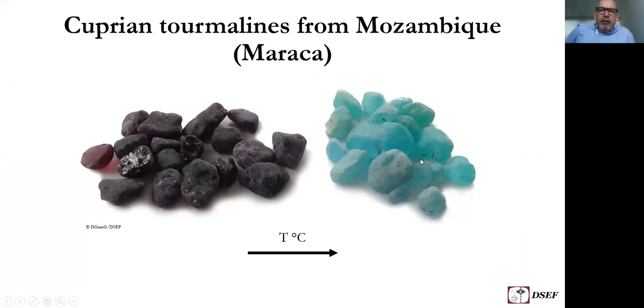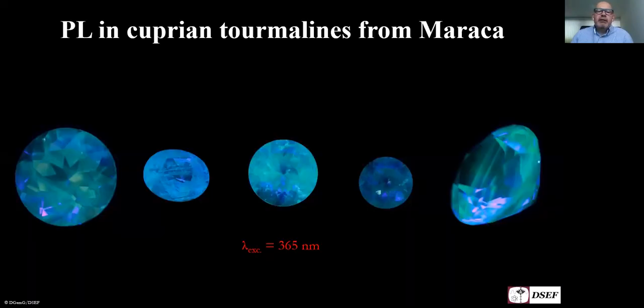Then there is an occurrence which is very close to the Mavuko occurrence, the occurrence which is located at the village called Maraca. There you predominantly find this type of stones, and if you heat treat them, they produce this very nice turquoise blue Cuprian tourmalines. And what is interesting about those is that these stones, and only the turquoise blue stones, show a distinct luminescence, fluorescence, when you illuminate them with long-wave UV light.